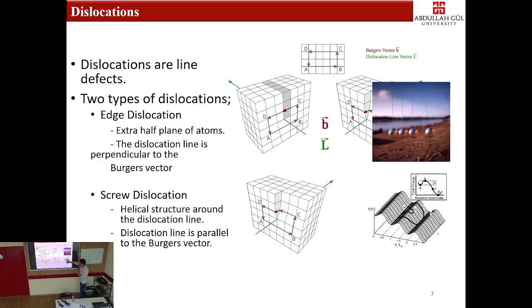But for screw dislocation, we have different energy landscapes. The formation is with two edge dislocation partials. These are called kink pair formation, propagation, and at the end, we have all screw formation. But one thing I forgot to say: do you think we can see cross slip in edge dislocation?